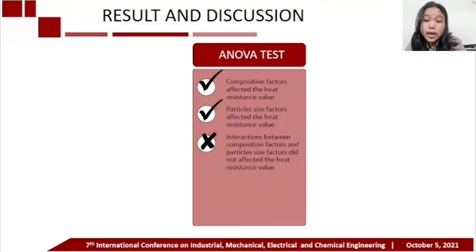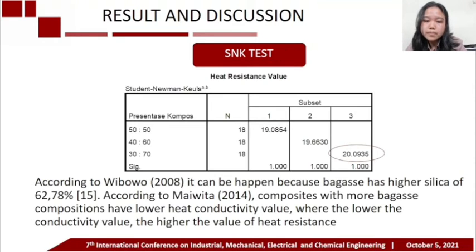Based on the result of the ANOVA test, SNK testing is carried out on composition factors and particle size factors to find out at which level has the most significant effect on the value of heat resistance. The SNK test shows that the composition factor of 30% rice husk and 70% bagasse has a higher value among the other levels of the factor. According to Wibowo in 2008, this can happen because bagasse has a higher silica content of 62.78%. According to Maiwita in 2014, composites with more bagasse composition have a lower heat conductivity value, where the lower the conductivity value, the higher the value of the heat resistance.